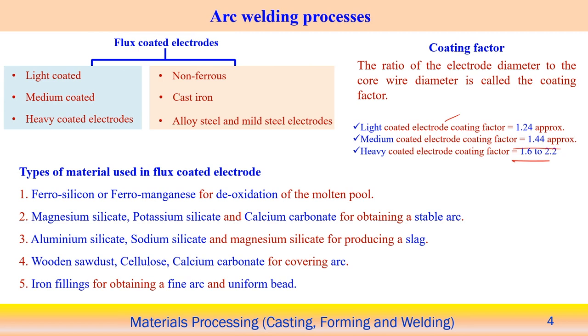But for the types of material used in the flux coated electrode, we see materials like ferrosilicon and ferromanganese, and that helps in deoxidation of the molten pool. Magnesium silicate, potassium silicate and calcium carbonate help to stabilize the arc during the process. Even we can use aluminum silicate, sodium silicate and magnesium silicate, which produce the formation of slag, easily converted to oxide, so that it is easy to remove after solidification.